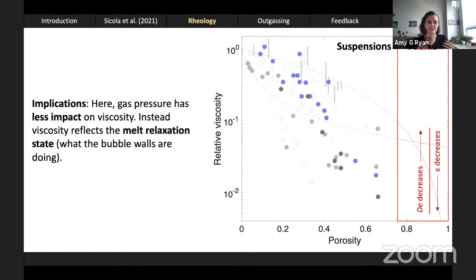To summarize, here gas pressure has less of an impact on viscosity than maybe in Stefania's work, for example. Instead, the viscosity really reflects the melt relaxation state. Effectively, what are the bubble walls doing and how can they respond to deformation? I've plotted here the range of viscosities I measure, and you see that it covers almost an order of magnitude, and that's solely a function of the flow conditions, parameterized as the Deborah number and the total strain that I imposed on the system.